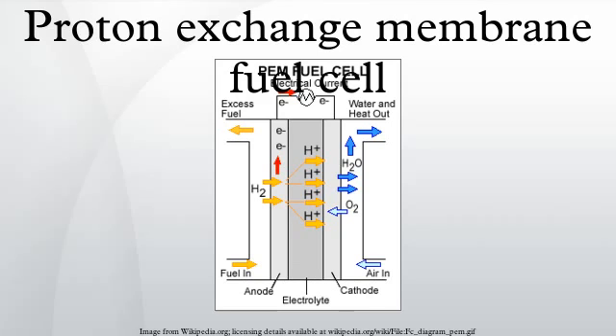Very recently, a new class of ORR electrocatalysts has been introduced in the case of Pt-M systems with an ordered intermetallic core encapsulated within a Pt-rich shell. These intermetallic core-shell nanocatalysts were found to exhibit an enhanced activity and, most importantly, an extended durability compared to many previous designs. While the observed enhancement in the activities is ascribed to a strained lattice, the authors report that their findings on the degradation kinetics establish that the extended catalytic durability is attributable to a sustained atomic order.